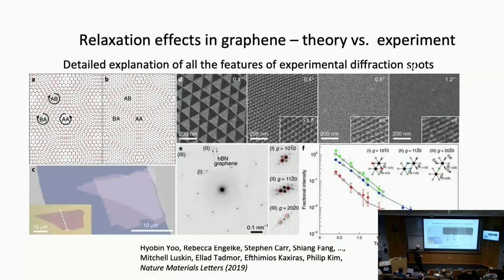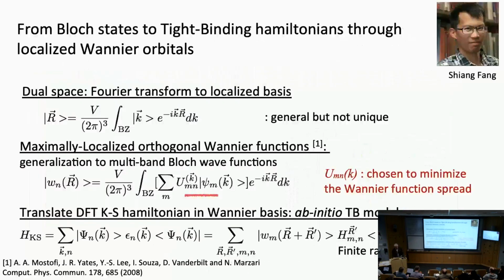Basically, all these dots from scattering experiments, diffraction spots, contain a lot of information about the local structure. And when you analyze the shape of these dots or the sub spots in each one of them, you recover this information and you can compare it to theory, and theory and experiment are in very good agreement. So it's not just pretty pictures that I showed you. We really have quantitative agreement.